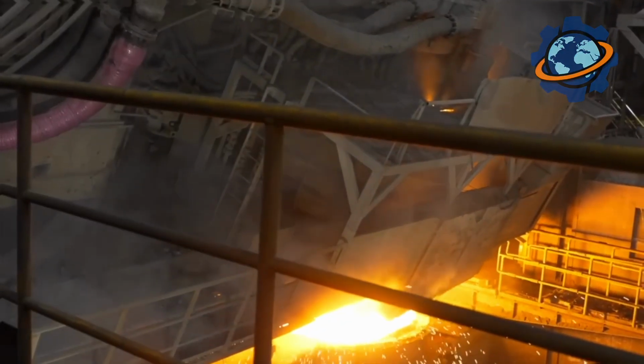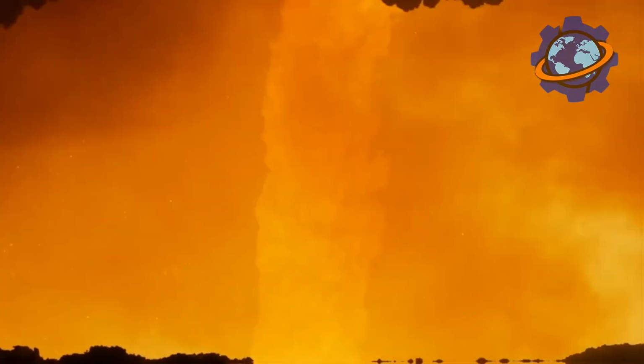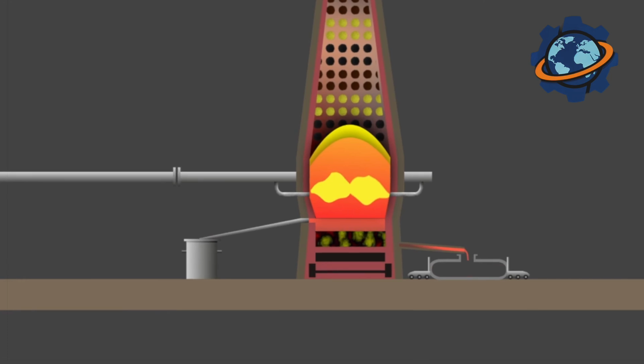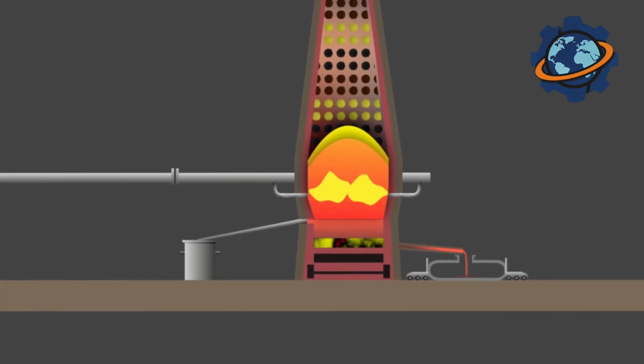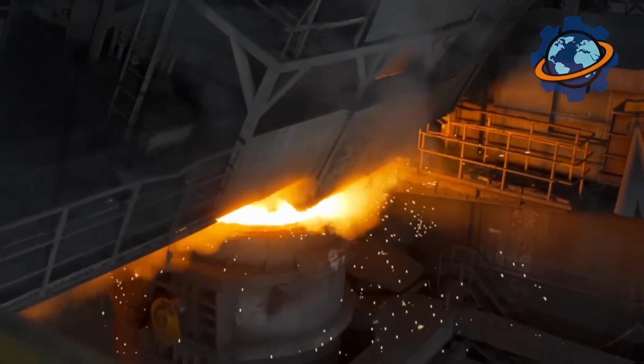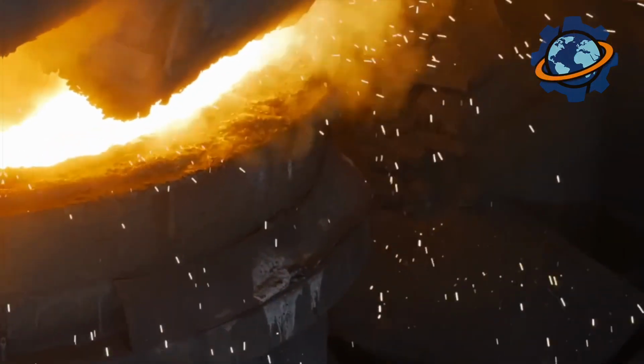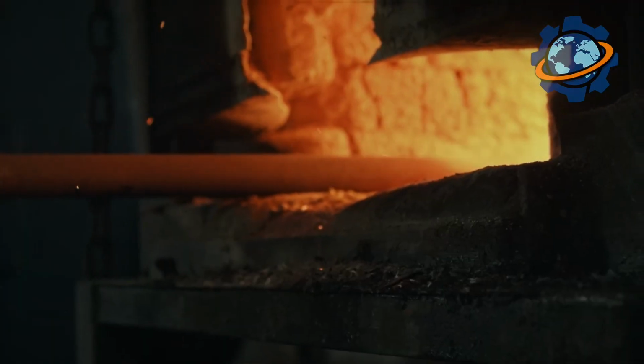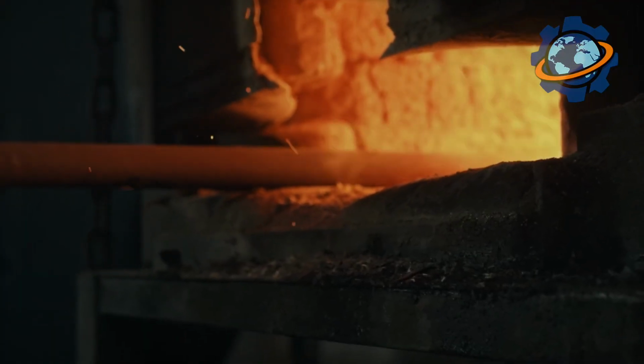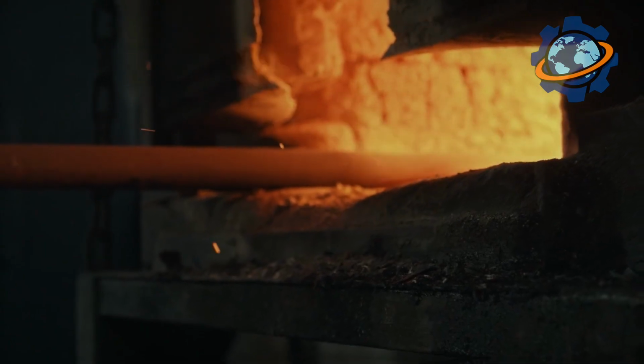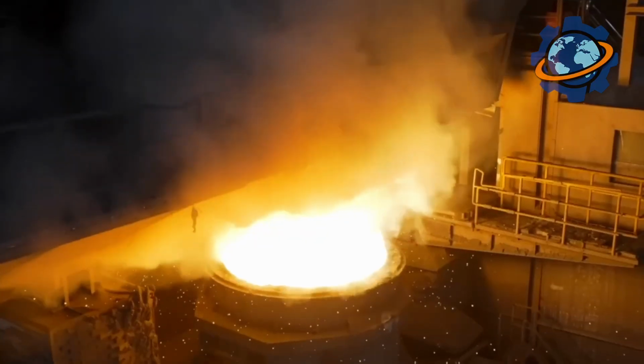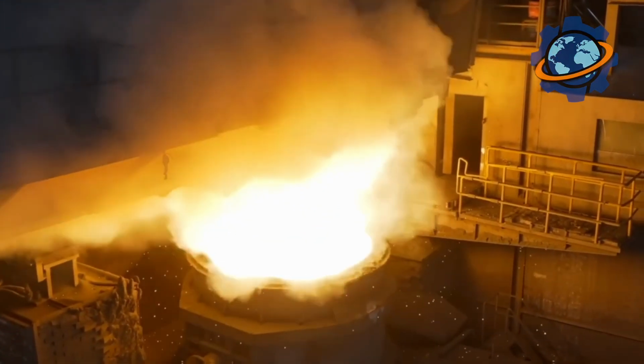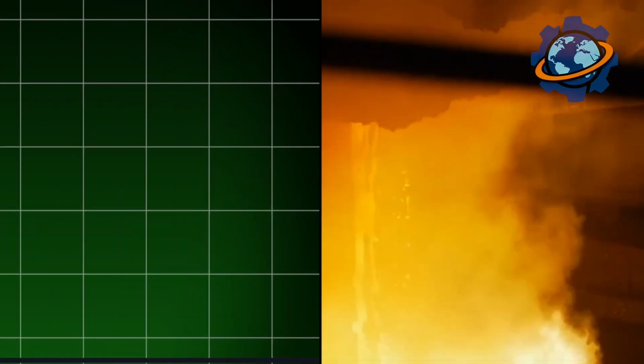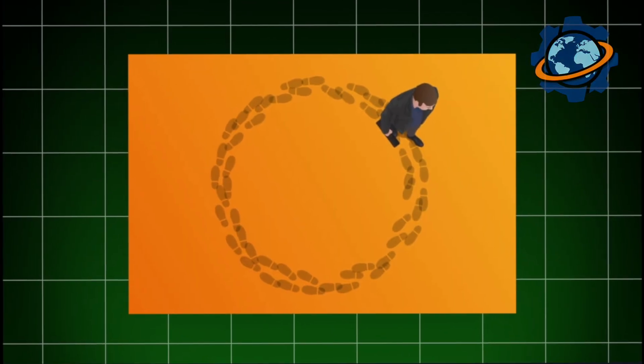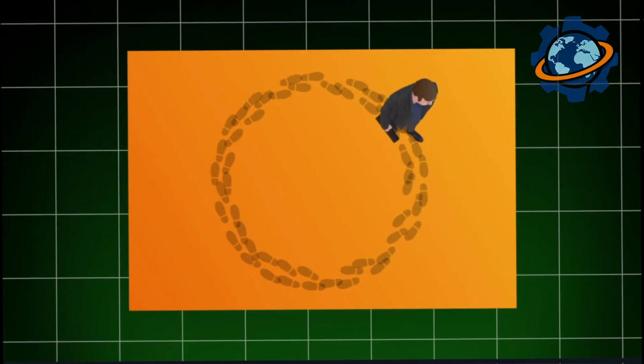A blast furnace is an amazing operation that produces more than just pig iron. The byproducts are just as important. The blast furnace slag, which we've already mentioned, becomes a valuable raw material for making cement, building blocks, and road aggregate after it's cooled and crushed. The blast furnace gas that comes out of the furnace isn't just released into the atmosphere - it's cleaned of dust and used as fuel to heat the very same air that's blasted back into the furnace. It's a closed-loop system that makes the process more economical.